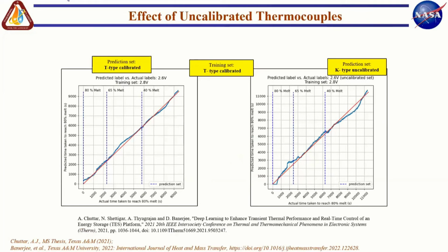We also found that if your thermocouple is uncalibrated, or if the calibration of your thermocouple goes off whack, you still tend to get pretty accurate data. And this is, I think, one of the biggest advantages of using a machine learning prediction engine. If you are going to use a corresponding CFD model, inaccuracies in your temperature measurement can actually end up with catastrophic failure in your predictions. On the other hand, because machine learning models are based on behavioral models, they don't care as much about the actual temperature value as about the trend in the temperature time trace. And so a K-type uncalibrated thermocouple, we did those measurements and compared it against calibrated data, also gave us pretty low errors in our predictions.